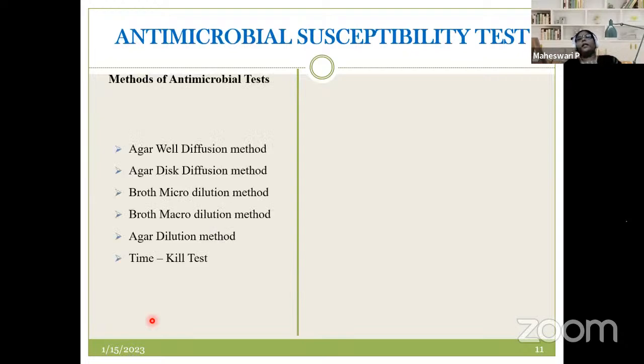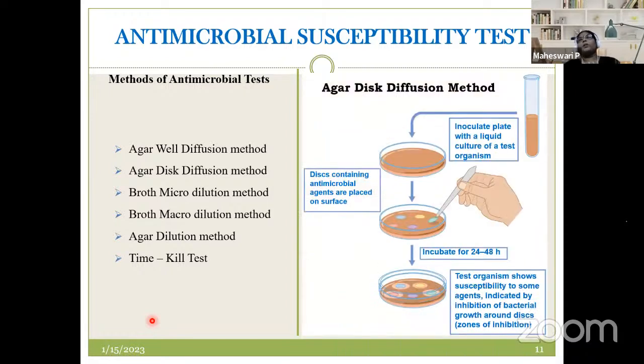Now there are several tests for this antimicrobial part, and among those we have chosen the disc diffusion technique, where the bacterial culture will be in a petri dish. We take the agents in the form of a disc and place them. We incubate for about 24 to 48 hours so that you can see the zone formed. That zone of inhibition, we need to calculate it, which clearly tells us how much the growth of the bacteria has been inhibited. So based on that, we have taken titanium dioxide and made the synthesis.